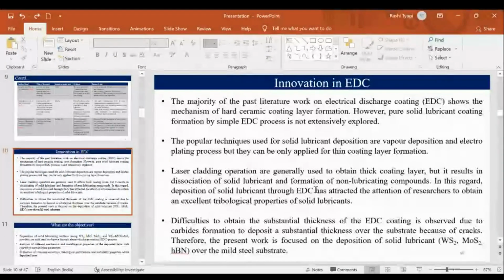We didn't use hard powder. Also, we can't use the other processes for solid lubricant. You can use physical vapor deposition or chemical vapor deposition for solid lubricant, but they can only give you a thin coating. So for thick coating, an innovative technique has been developed, that is the EDC process, utilizing the deposition of solid lubricant powders to obtain excellent tribological properties.